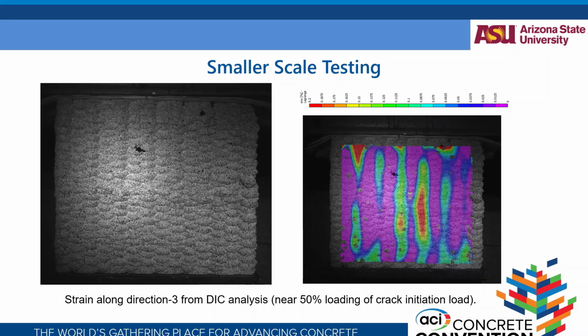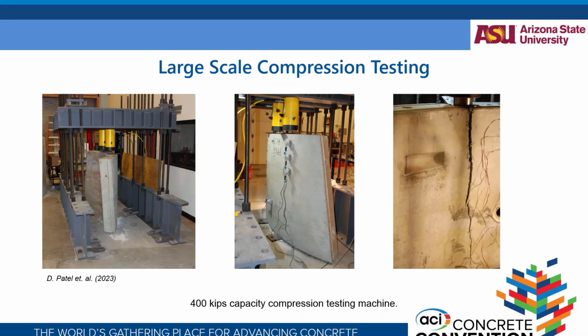In future, we are planning to move this into a larger testing scale, where the heights are going to be significantly larger rather than the width and dimensions, because the dimensions we are using right now are in the range of, I think, 13 inch by 4 inch, which is limited by the load taking capacity. If you go for 7,300 psi, it will most probably hit the 400 kips capacity. So we are still going to do similar sections, but with larger layer height to make it a higher height to depth ratio.